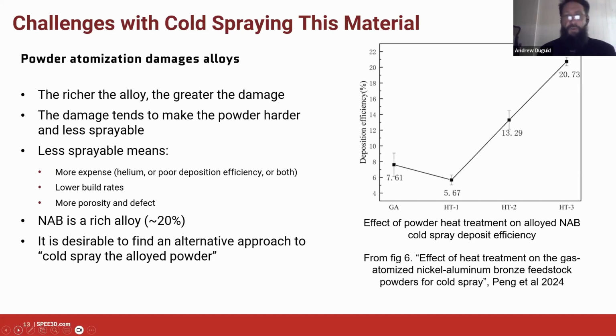So, for us, it's quite desirable to find another way around that. The graphic on the right there is from a bit of work we were lucky to find, on the deposition efficiency of cold sprayed NAB with heat treatments. You can see that the heat treatments can make a big difference. It has gone up from about 8% to as much as 20% there. So heat treatment can be an effective route depending on the alloy, but we might go on to the next slide.